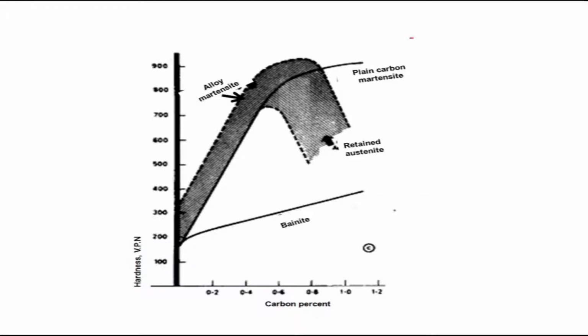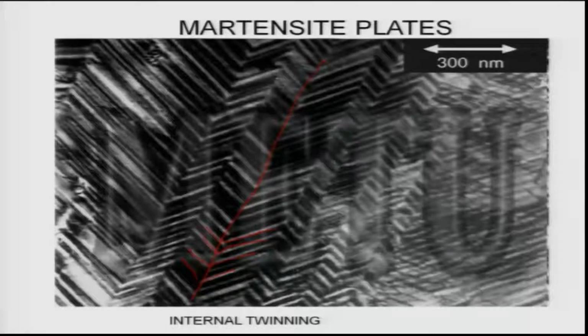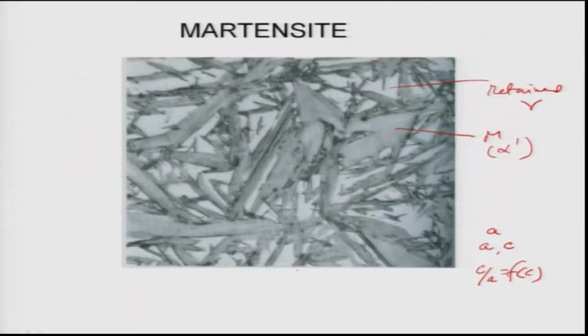So first of all, why do you have retained austenite in the microstructure? Let us also discuss that part, because that is very important; it dictates the total hardness of these martensites. Remember, martensite forms from high temperature by quenching, therefore it forms by a shear deformation process. And because the undercooling is very large, you are quenching the gamma phase from 950 degrees to room temperature.